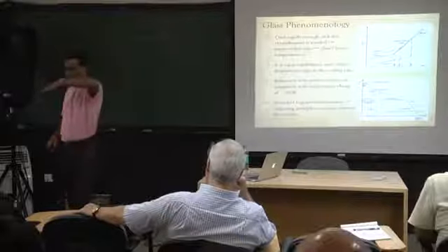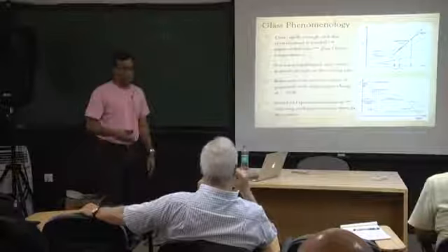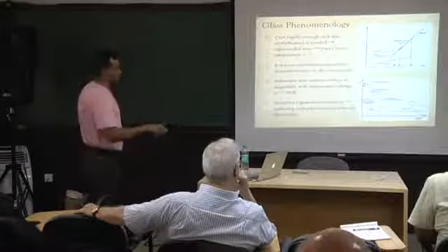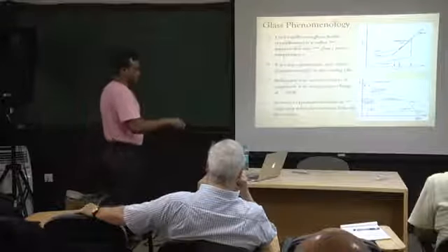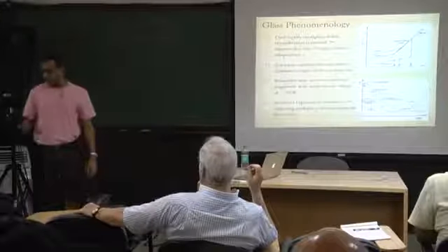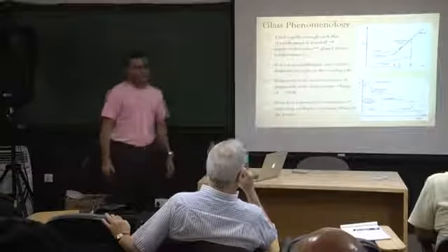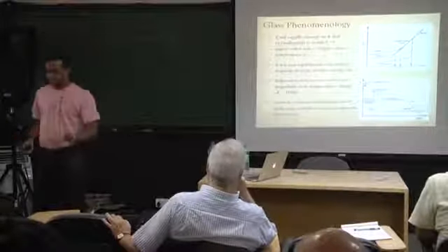The plateau is not a real plateau, it's actually slanted. So there is relaxation happening, and that's a regime called beta relaxation, also very controversial, and these things are not very clear. Then eventually the correlation function decays at a longer time scale. That's called the alpha relaxation time. The clear-cut difference between beta and alpha is not very clear, as you probably saw already in Ranjini's talk, but in this talk I will only be focusing on alpha relaxation and the related story.